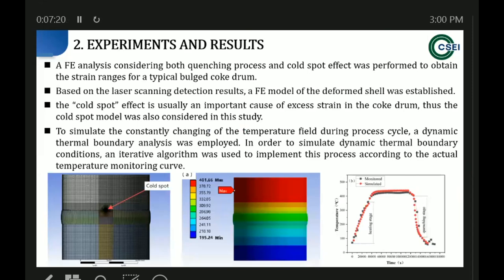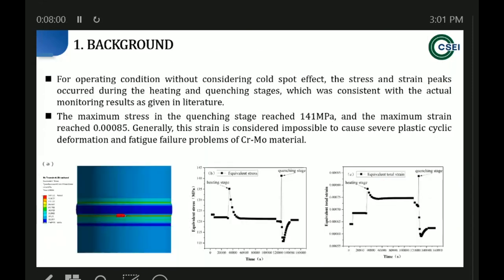And next, we perform FE analysis, and we consider both the quenching process for normal operating condition and also the cold spot effect. Here we establish the FE model, considering the deformed shell, and we also consider the cold spot effects during the quenching stage. We also use dynamic thermal boundary analysis to make sure the simulated temperature curve is the same as the measured one. So at last we calculate again and again, and then we get the temperature and stress profile. And here we can see the results.